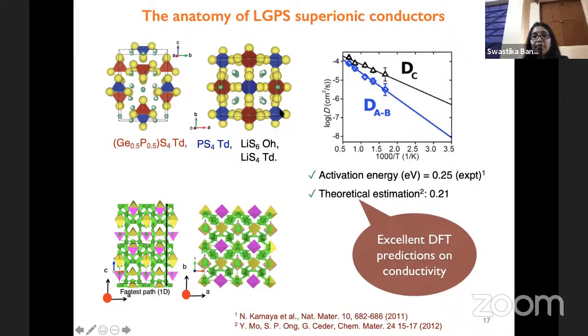So this kind of system, if we want to realize it, we have two strategies. We can computationally design the framework and experimentally study it. And in the next step, we can make a successful device with a lot of consideration of minute details about the reactivity, the stabilization at the interface, the resistance at the interface, all those kinds of understanding of the device setup. So here I have shown a computational result from ab initio molecular dynamics, which successfully predicts that these are the frameworks which can give you very good diffusivity for the lithium ions. And the activation barrier estimated from theory and experiment match pretty well. So that says the excellent prediction